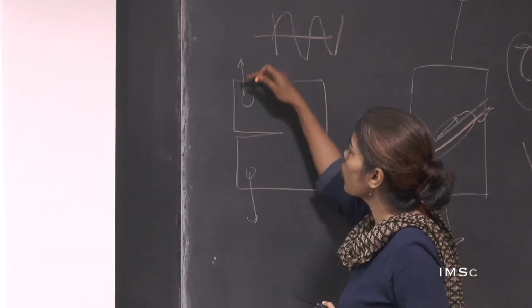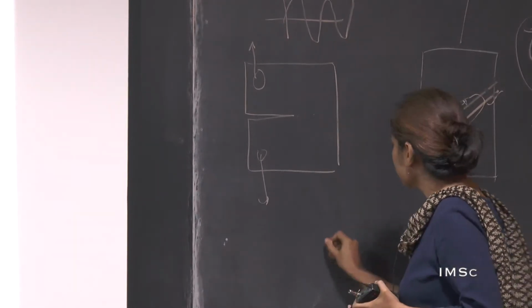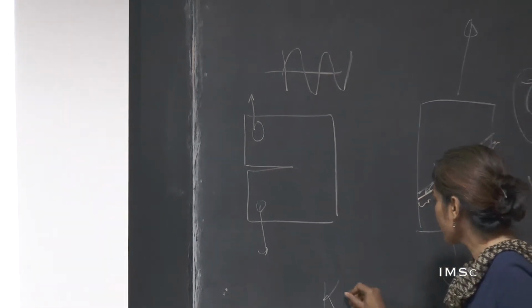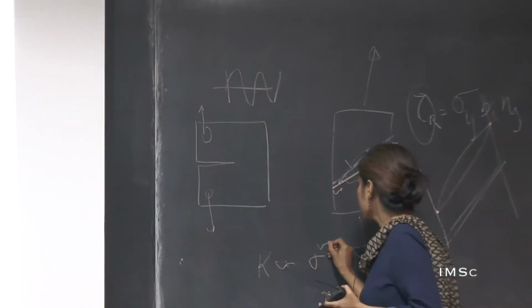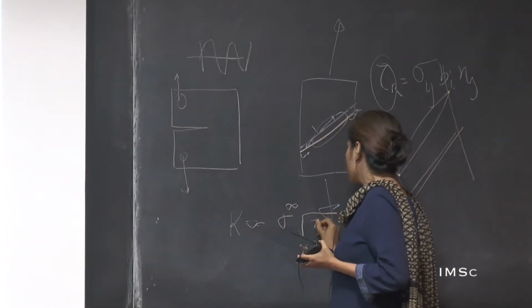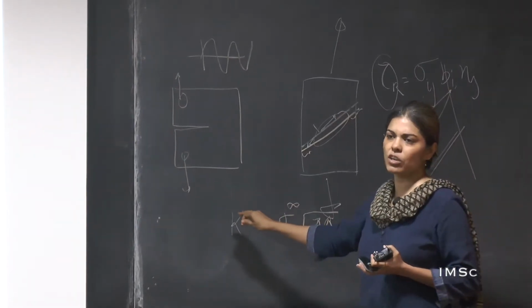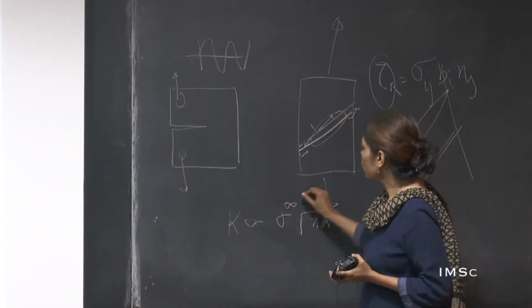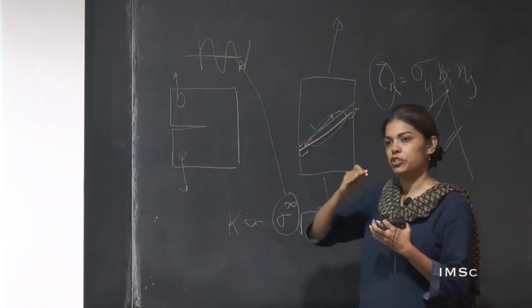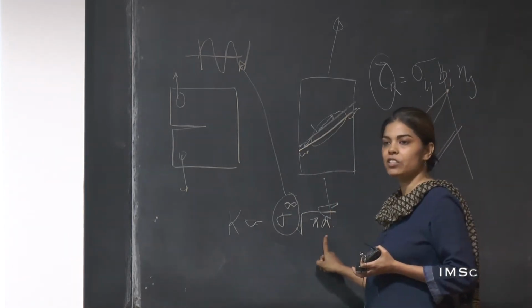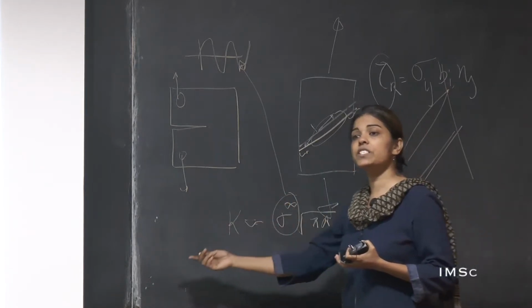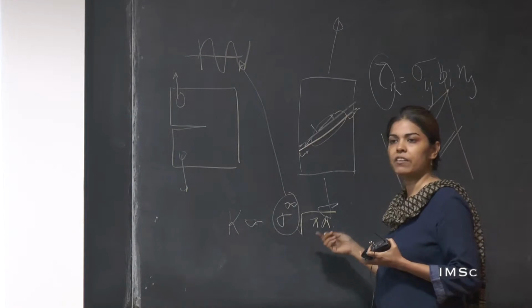Now, based on what load you have applied, the stress intensity factor goes like the remote stresses acting times root pi a, with various constants involved. So if your sigma infinity has a cyclic behavior, with an amplitude, for a given crack length you will have an amplitude of K as well, which is evolving with an evolving crack.